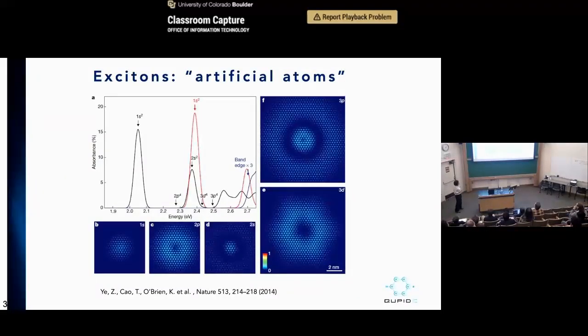Just to give some visualization of what this exciton wave function looks like. As I mentioned, you can think of them as an artificial hydrogen atom, and this is a calculation done on a single layer tungsten diselenide. You can see this orbital or wave function very much like your hydrogen orbitals, like 1s, 2p, and so on. The key difference is that because of the dielectric screening, you're going to have a wave function that is more delocalized compared to your hydrogen atom. In this particular case, they are on the order of 1 to a few nanometers depending on the excitonic states.